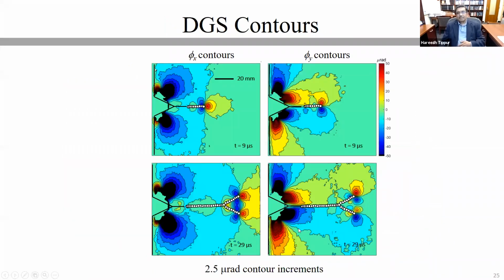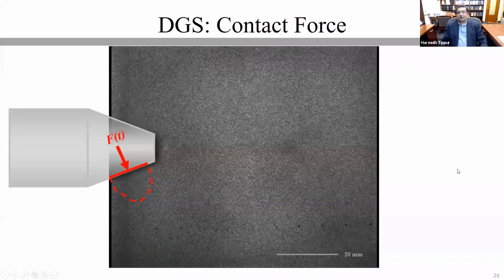Here are some still images from that particular experiment. The edge of the specimen is highlighted, and the various dots that you see are those where the crack was at a previous instance of time. The top row corresponds to the mother crack. The bottom row corresponds to the crack that has already branched and has produced 2 daughter cracks. So we have 1 bifurcation event in this experiment.